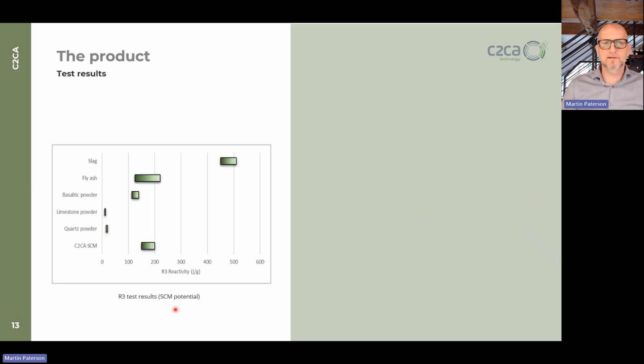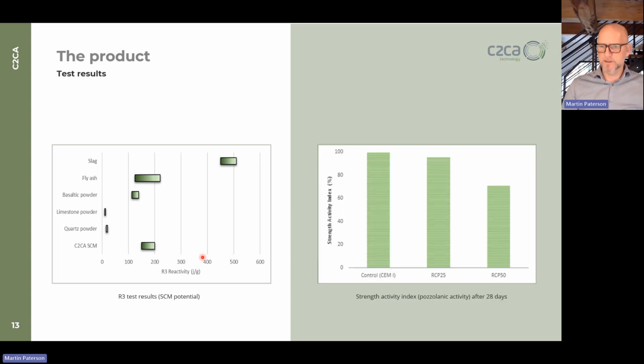We have also tested a lot on the reactivity. You can see here, down here, that we are almost within the range of fly ash already after the R3 test. But please keep in mind that this material produced so far was done without a comprehensive crushing and without the dynamic activation. So we are very sure that we can move this bar up the ladder and get closer to the SCM potential of slag afterwards.